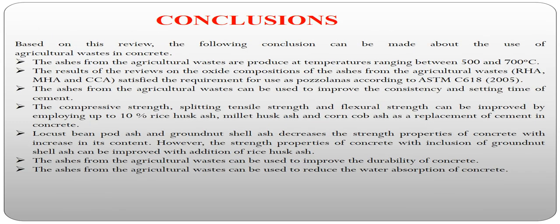In conclusion, based on this review, the following conclusions can be made about the use of agricultural waste in concrete. The ashes from the agricultural waste are produced at a temperature range between 500 to 700 degrees. The result of the review on the oxide composition of the ashes from agricultural waste satisfies the requirement for use as a pozzolana according to ASTM. The ashes from agricultural waste can be used to improve the consistency and setting time of cement.